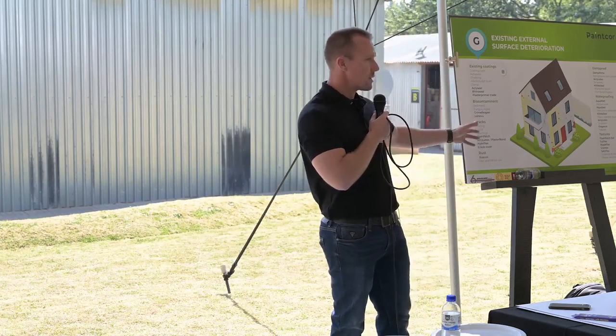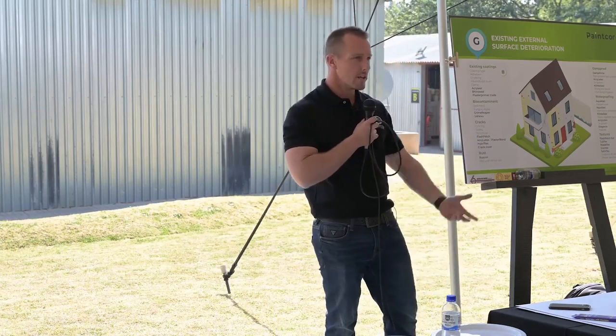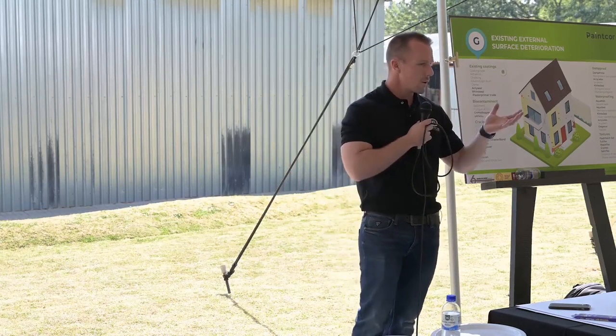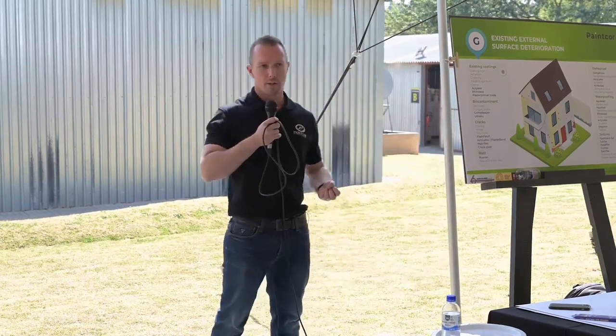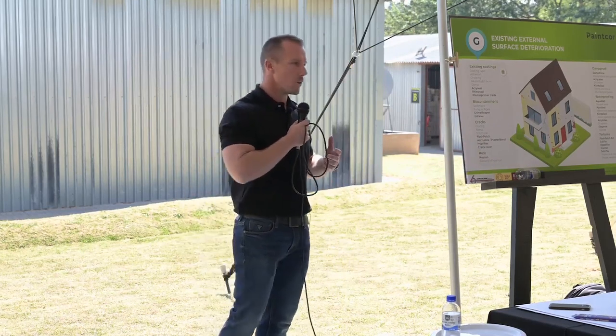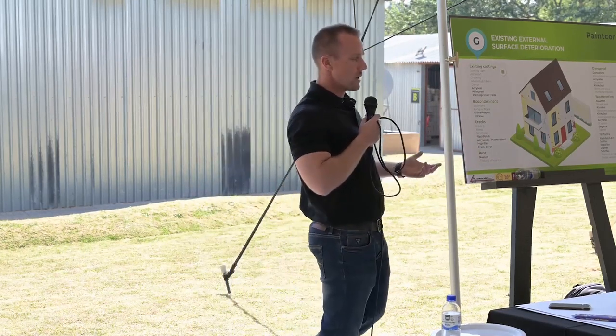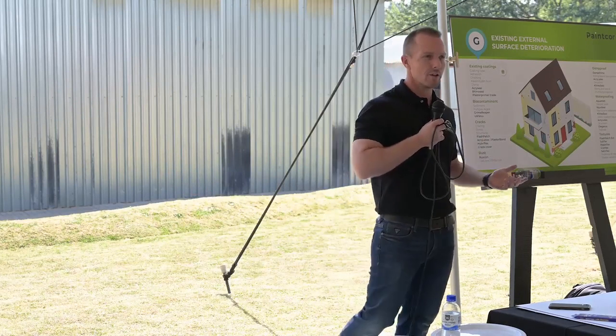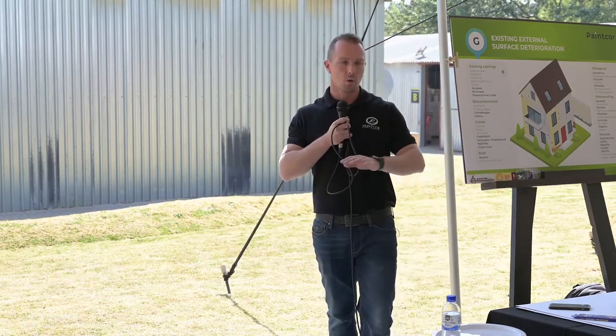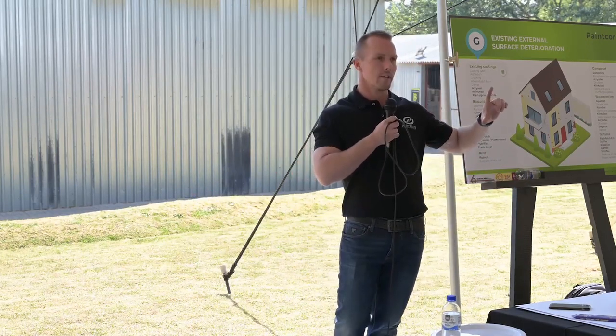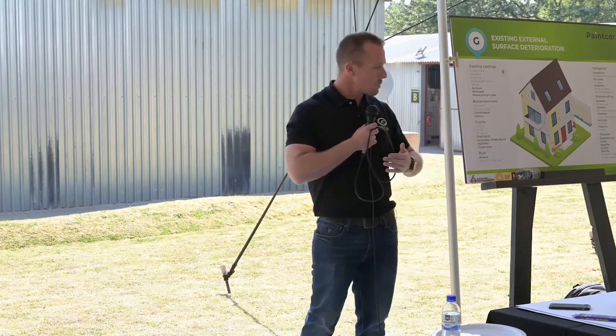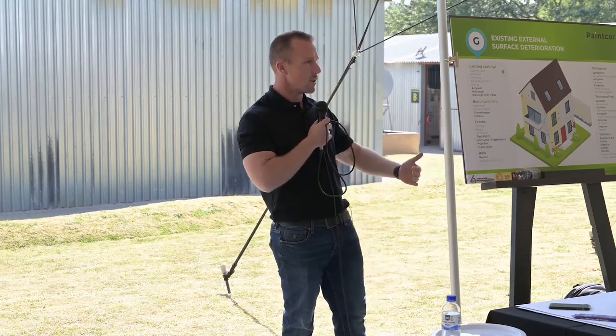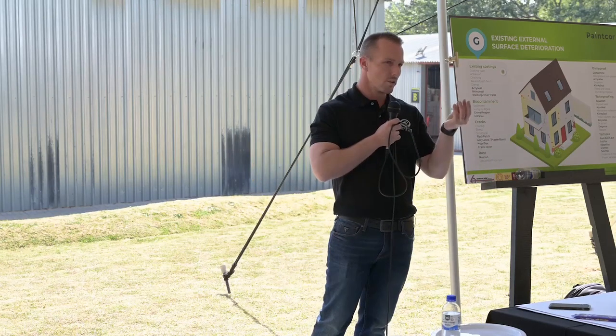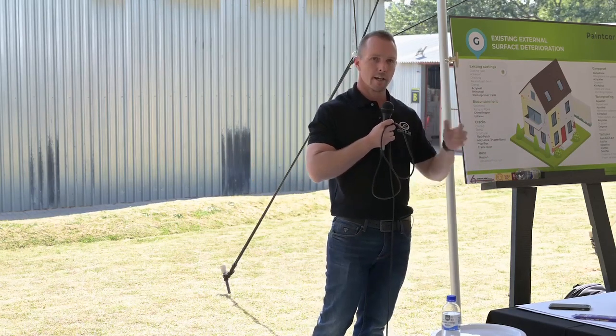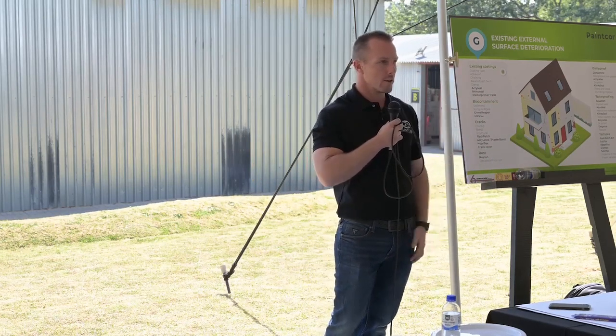You would also use that on porous grouting or porous tile work on balconies, for example, where you suspect that water is seeping through these surfaces. I've seen waterproofing jobs which would have otherwise been a 60 to 100,000 rand retiling job, sorted out with one tin of clinker seal. So again, you're pouring that on consecutive coats, wet on wet. It's ingressing into the pores of the tile and the surrounding grouting, solidifying and stopping water going through it.